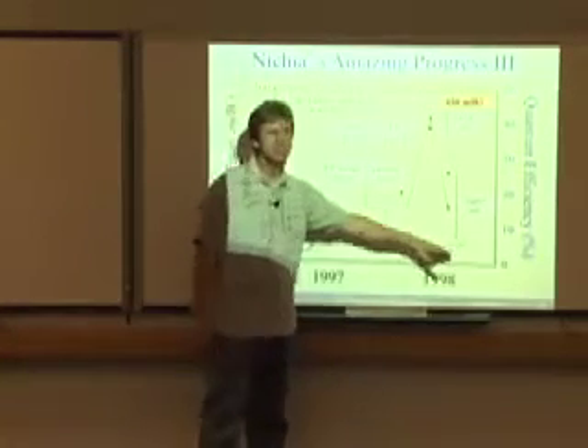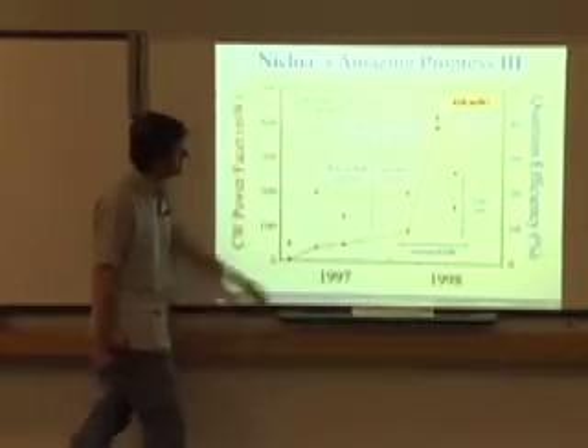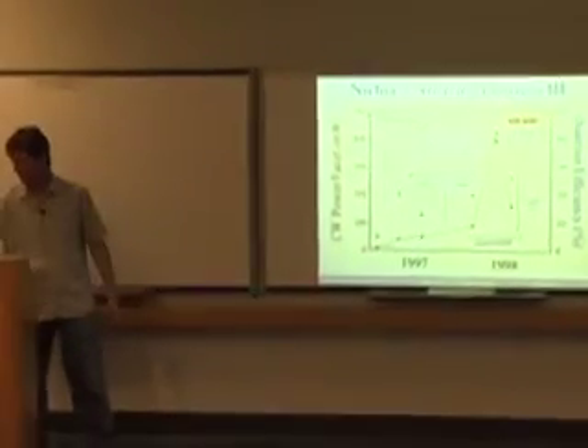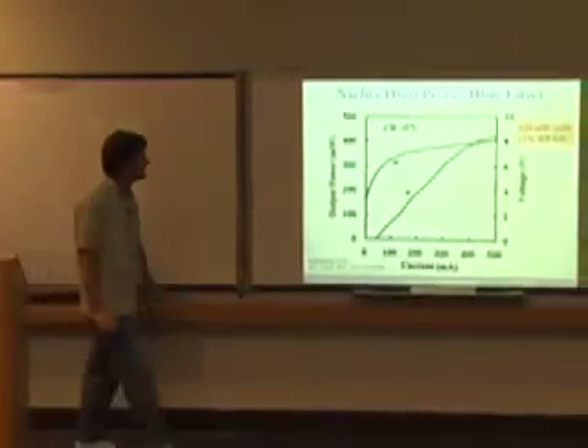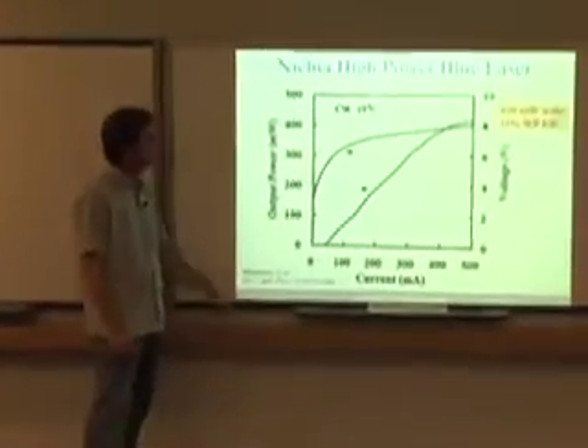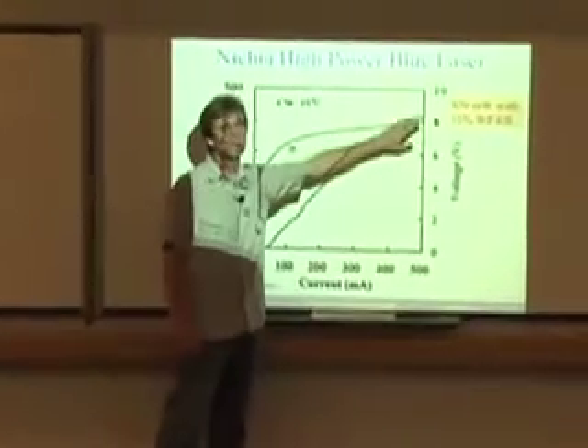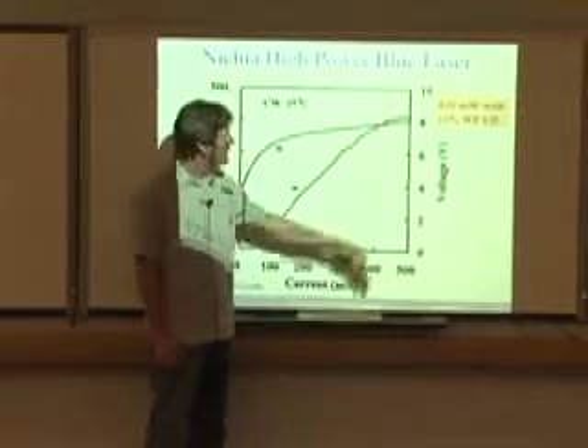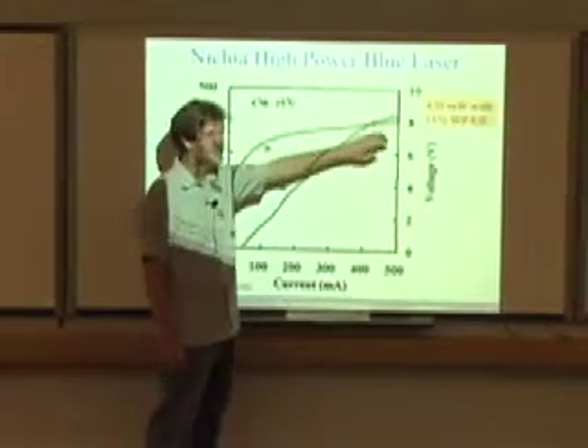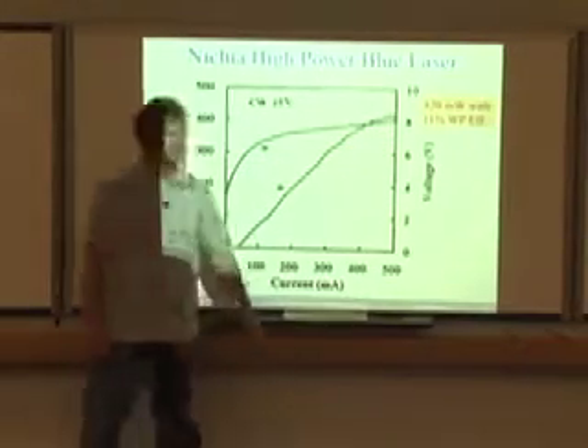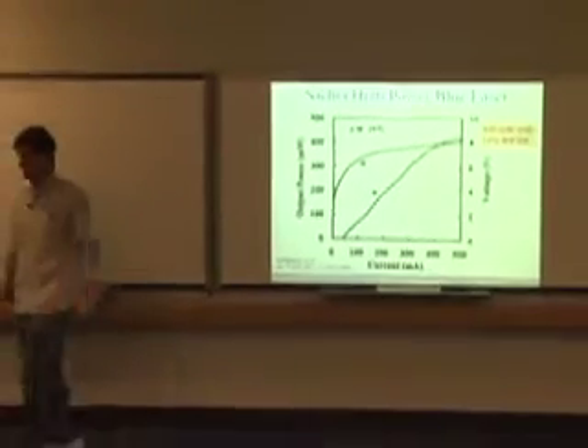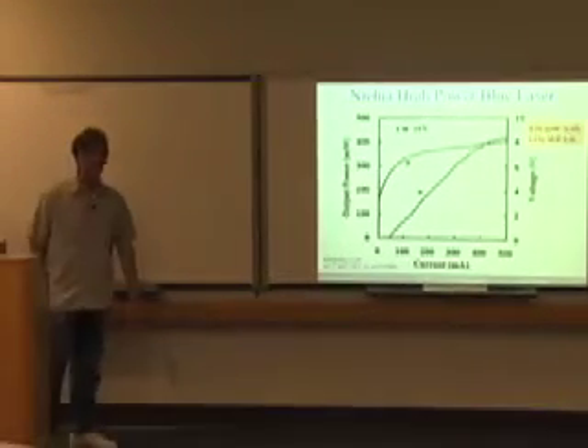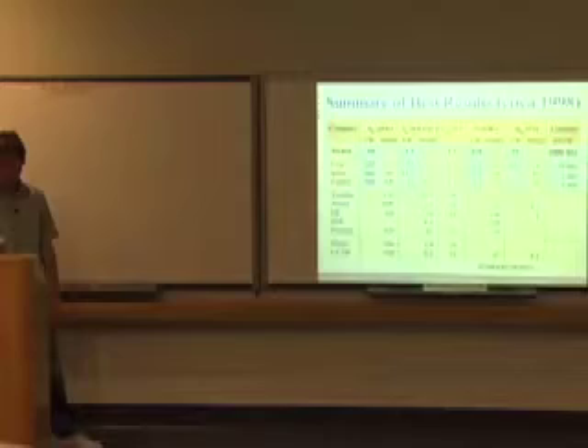And this is actually using an uncoated facet on one side and an HR coating on the other side. This result is with the gallium nitride substrate that I just mentioned before. So this is an example of the high power blue laser, 420 milliwatts, 11% wall plug efficiency at the time. I think you were telling me earlier, 30% is now the record from Nichia. But even back in '99, 11% was pretty remarkable.